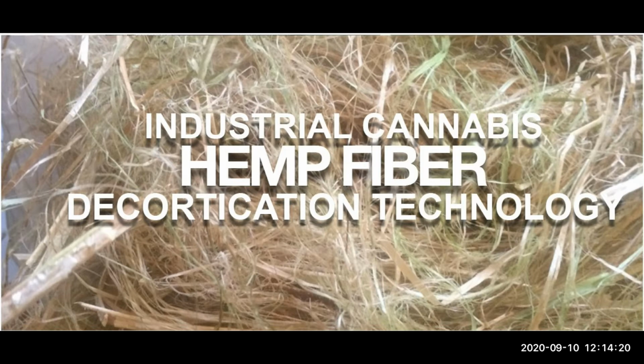Right. This is where some of the industrial consumers had come up asking for fiber lengths that were 2.5 to 6 inches long. And the existing technology just can't do that. It's physically impossible. The hammer mills will put out shorter fiber, but the maximum length is 2.5 inches. And these guys were looking for long fiber for biocomposite panel manufacturing. Okay. So kind of like doing a weave type of thing, or laying the fibers out lengthways. And the longer the fiber, the more tensile strength.